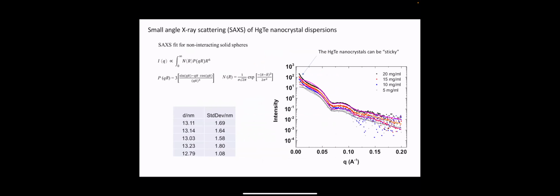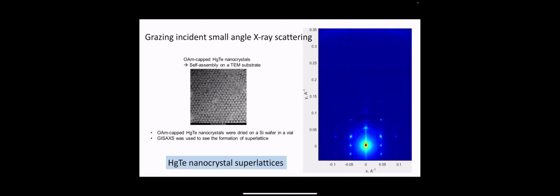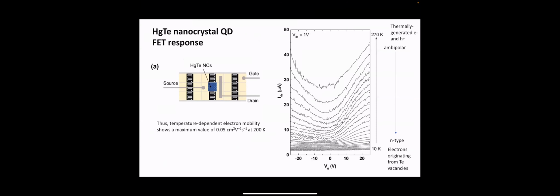Again, we can do pretty decent small angle X-ray scattering measurements on dispersions of these. You see that uptick in scattering intensity at low Q. So there's some attraction between particles, which ideally we don't really want, but we can still form superlattices even with that. And so, yeah, I guess I don't have a whole lot of X-ray scattering data in this talk, but this is some GISAXS data of a superlattice of mercury telluride nanocrystals. So you can make superlattices.